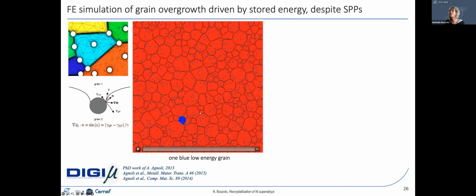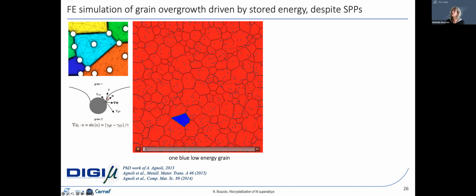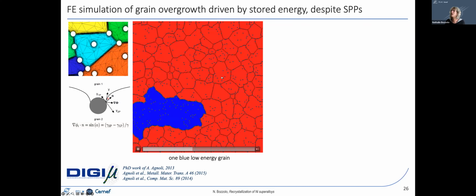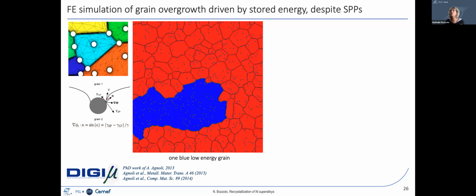So this could be simulated also. So here you have a very simple simulation we made some years ago with a microstructure made of grains with second phase particles, which are these small gray features. And in this microstructure, one grain has been attributed a stored energy level very low compared to all other grains. So the red grains have stored energy, the blue one has no stored energy, let's put it like that. And this is how the simulation works. You see that the boundaries between two grains with a similar stored energy level are pinned by the second phase particles, but the grain which has an additional driving force due to the stored energy consumption can grow while the other ones stagnate.